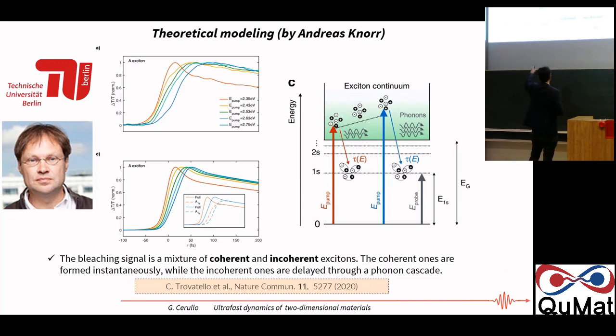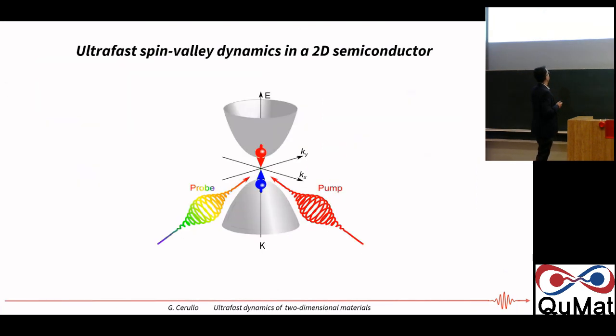So the coherent excitons, of course, are formed instantaneously, while the incoherent ones are delayed through a phonon cascade. And with this model, and using parameters of the materials, this could reproduce quite well our experimental result and our pump energy dependence of the exciton build-up. So we really can resolve, thanks to this high time resolution, this very fundamental process of building up of the excitonic bleaching. So this is the first experiment.